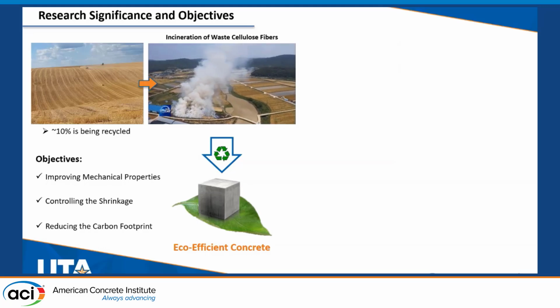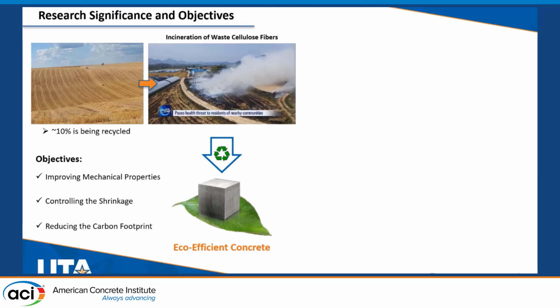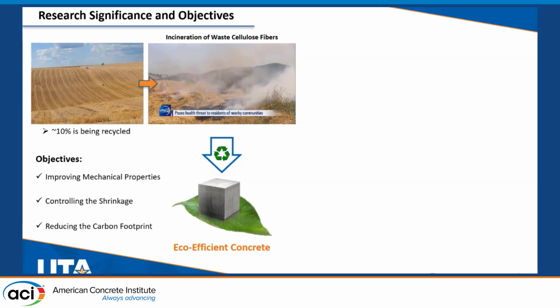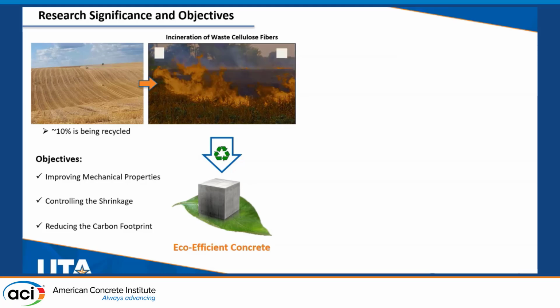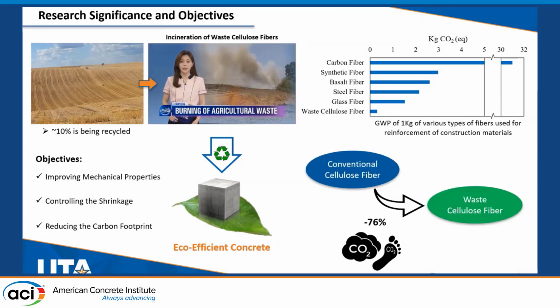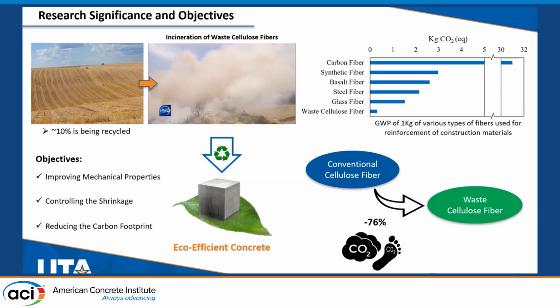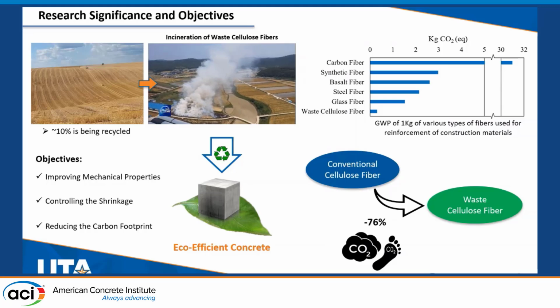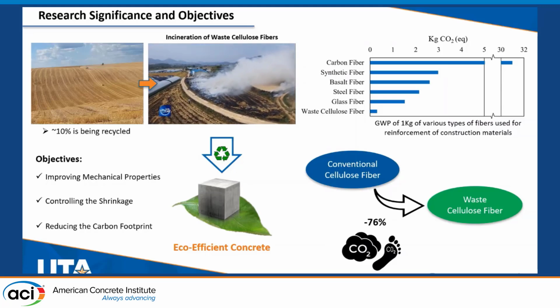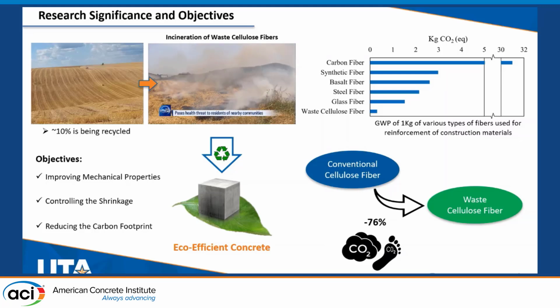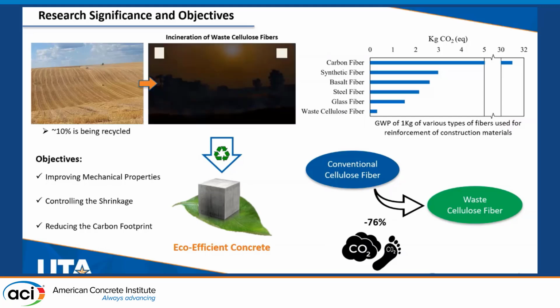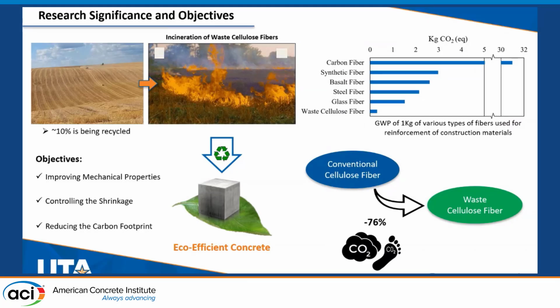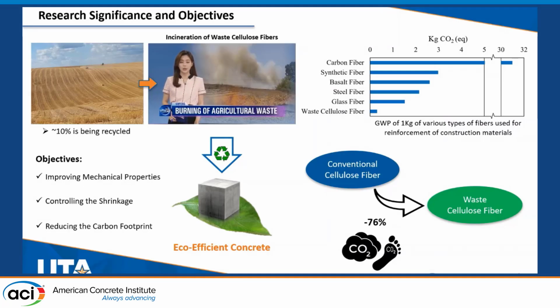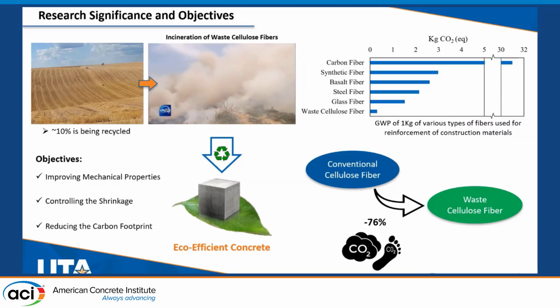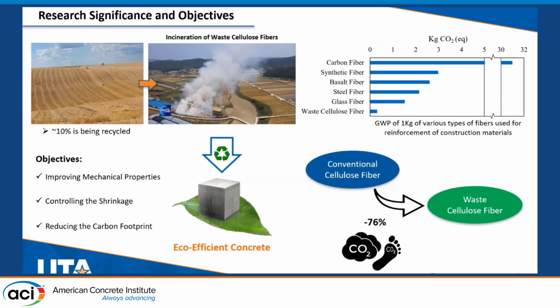To reduce the emission of carbon dioxide and address the environmental issues associated with that, we use these fibers to produce eco-efficient concrete with enhanced mechanical and shrinkage performances. As you can see on the right side of the slide, these fibers also have a substantially lower carbon footprint compared to the most common types of fibers that are used for producing fiber-reinforced composites. Most specifically, compared to the conventional cellulose fibers, these fibers have a lower carbon footprint, on average about 76%, that adds to the importance of these fibers to be used for producing fiber-reinforced composites.